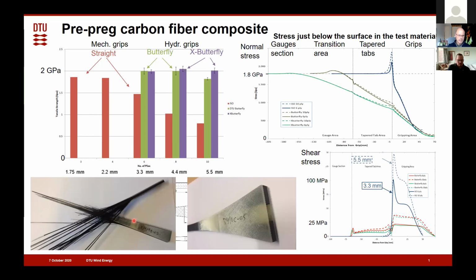And here is showing the failure of this composite here. So you can see a lot of fiber failure and splitting of the test sample. So it can be hard to identify where the failure happened. For the thickest one, we can see that we have this shear failure between the tab and test material, and for the butterfly shape, we also have splitting along the UD fibers. So this is for the prepreg carbon fiber composite.